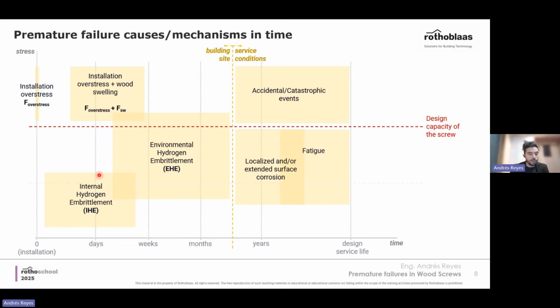In the same period, in the period of days, we start in the construction site. We can start having exposure to moisture or humidity, and we can add the overstress that maybe was not enough to break the screw, adding swelling. The swelling of the wood could lead as well to breakage. In this case, we're talking as well about surpassing the design capacity of the screw, and that could lead to breakage.